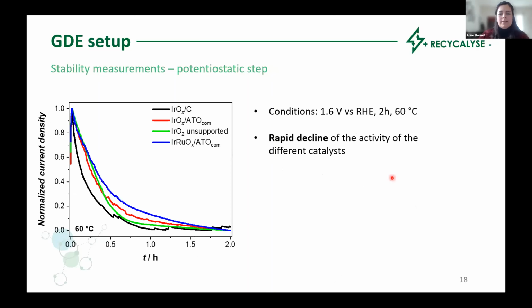And then we wanted to test the stability of our catalyst, and we did it by holding the potential at 1.6 volt for 2 hours at 60 degrees. So this is quite harsh conditions for the catalyst. Unfortunately, we could not conclude so much out of these experiments, as all catalysts degraded within the first 30 minutes. We wanted to believe that it's not our catalyst that is performing so badly, but that it is rather something else causing this loss of activity.